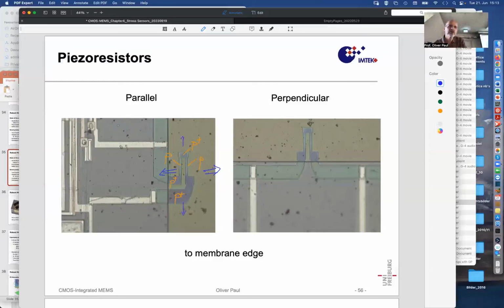But that longitudinal stress is going to be only nu, Poisson's ratio, times this perpendicular stress, perpendicular to the edge of the membrane. And nu for this 100 direction is actually quite low. It's 0.07. So this stress here is really small. It's 7% of the stress that we have in this sigma xx direction. We call that x.